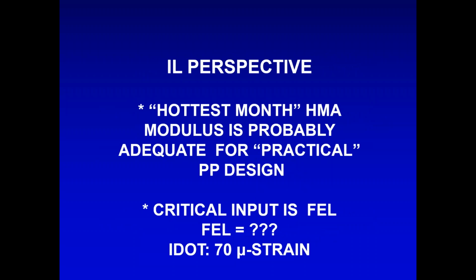Our perspective on perpetual pavements, that's hard to say quickly, in Illinois is this. We look at the hottest month of the year, which is July. We predict the modulus for that month and say, okay, what's the strain value for that particular temperature? And we compare it to our criteria. In Illinois, we picked 70 microstrain. That's a very conservative value, by the way. But that's the way we do it.